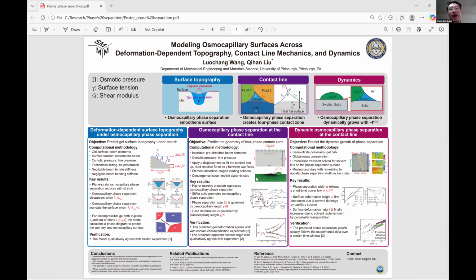We update the active boundary region with a moving boundary approach. And this model predicts that the phase separation width actually grows as a power law, and the surface height behaves non-monotonically. This result shows strong agreement between simulations and experimental measurements from the other literature.